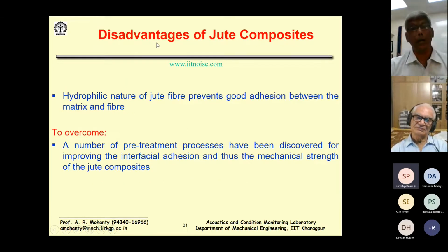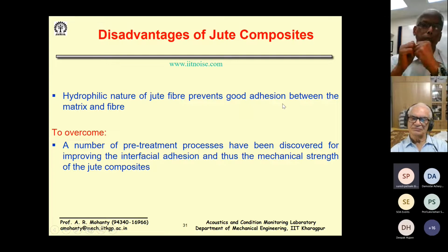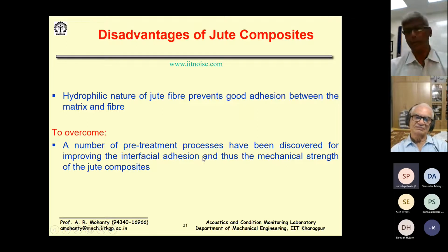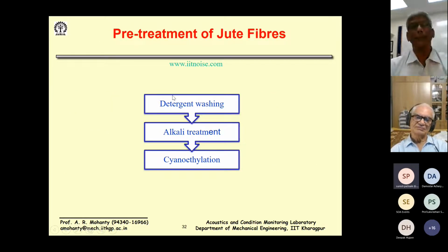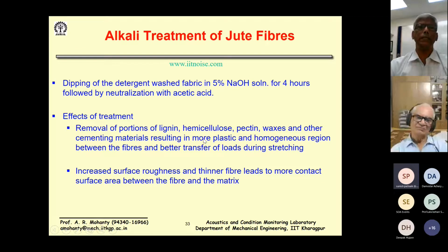Of course, the disadvantage is that because they are hydrophilic, jute prevents good adhesion between the matrix and the fiber. That is why a little bit of chemical pre-treatment has to be done to this material, and there is a recipe which we figured out: we wash it, do a certain alkali treatment with sodium hydroxide, and we mix certain chemicals, so that we get a good bonding. And this is what is required.